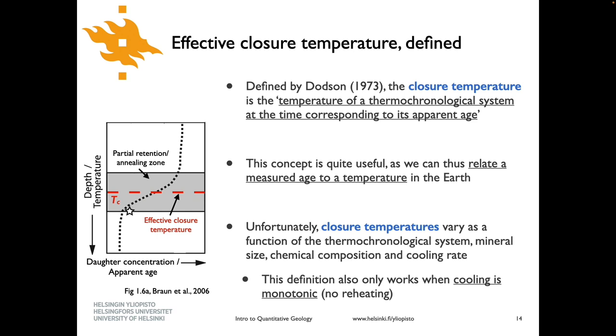So is it then that if you have a hot enough crystal, it's able to rearrange its lattice and fix those? It basically anneals the damage. It's the same as metals: if you heat them up, they will anneal damage. Crystalline material will also anneal the damage at higher temperatures. The temperature at which the annealing occurs will depend a little bit on the crystal that you're looking at. But for apatite, typically temperatures of more than about 120 to 130 degrees over geological time will heal the crystal damage. So you're looking at the concentration of fission tracks that occurred below temperatures of maybe 110 to 120. For zircon, it's a little bit higher, maybe around 200 to 240 degrees for the temperature at which the annealing is occurring.